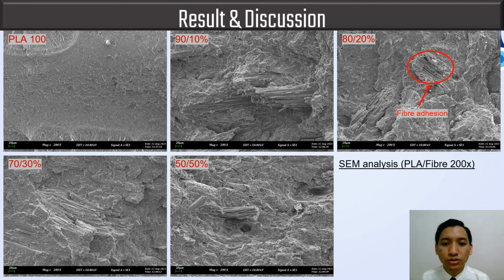The SEM photos also reveal the difference in size of the fiber bundles. We can clearly see that the 70-30% blend has the largest size of fiber bundles compared to the other compositions. The 80-20% and 50-50% blends have nearly the same size of fiber bundles. The 50-50% blend shows the fibers were not well distributed in the PLA matrix, which forms a void at the surface when stress is applied.